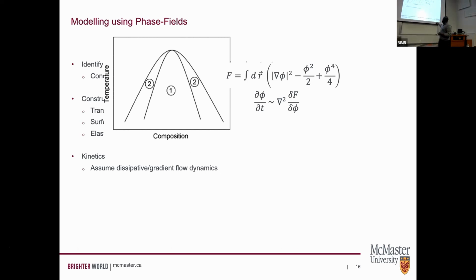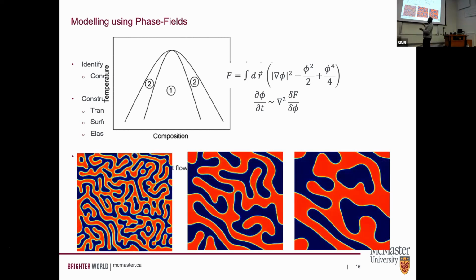Then I run these dynamics, and I get microstructure patterns that look like this. So here what we're looking at is from left to right, increasing time. Presumably, I started off by quenching my system into this two-phase region where I started off with some unstable fluctuations, and then they separated into one that, let's call this A-rich, and another that is B-rich, for example. So that, in a nutshell, is a phase field model.